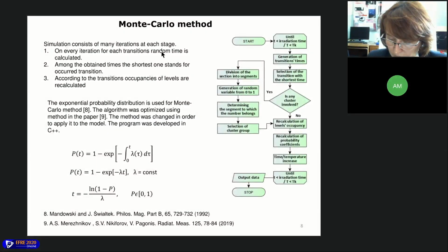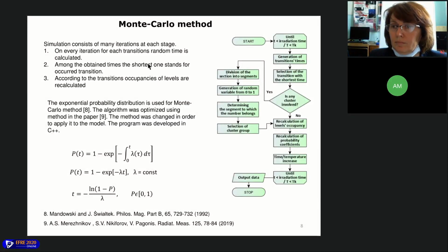We used Monte Carlo method for simulation of charge carrier transfer between different energy levels. Each stage is characterized by a set of possible transitions and ending condition. At any stage, iterations are executed until the condition is reached. On each iteration, random time is generated for every possible transition. Among the obtained times, the shortest one stands for the occurred transition. According to the occurred one, occupancies of levels are recalculated. The exponential probability distribution was used for random times generation, and the program was developed in C++.